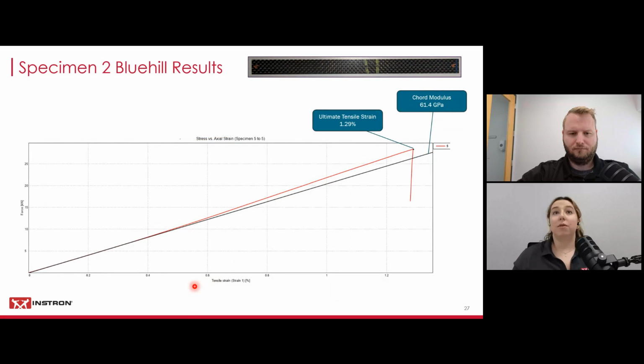Next, my smaller untabbed specimen, this line looks really great. It's really smooth. So this is an ideal case of using the clip-on. I don't really see many micro cracks. It was able to remain on during the entirety of the test. So we tested up to just above 25 kilonewtons at 1.29% ultimate tensile strain and a chord modulus of 61.4 gigapascals.